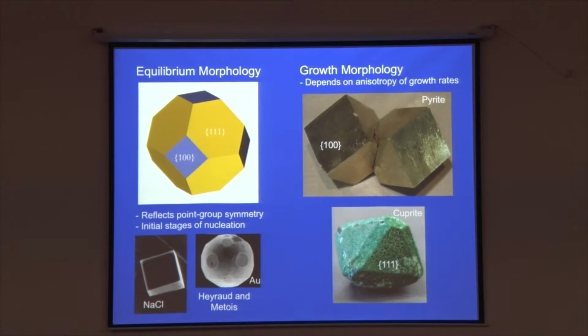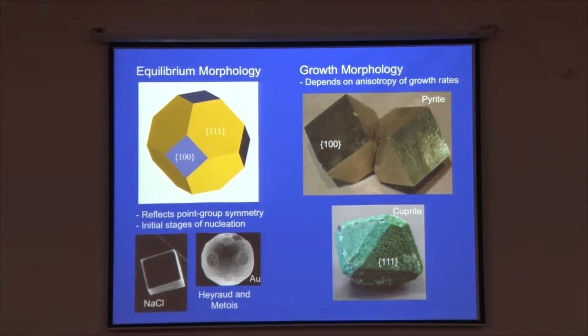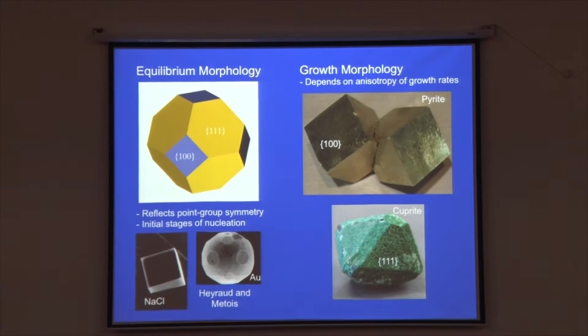The interesting thing is that during the early stages of nucleation, that is, when the crystal initially forms, there are two energy terms involved: a barrier term and the volume free energy term, which basically drives the formation of the crystal. The barrier term, namely that you are creating new surfaces, means that the crystal would like to adopt a shape that has a minimum surface energy, or interfacial energy, in the growing medium.